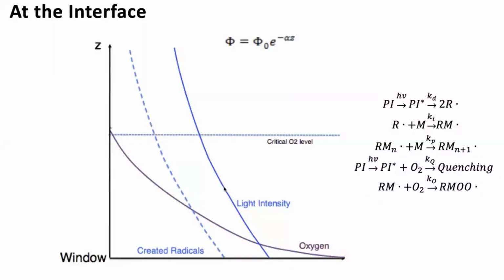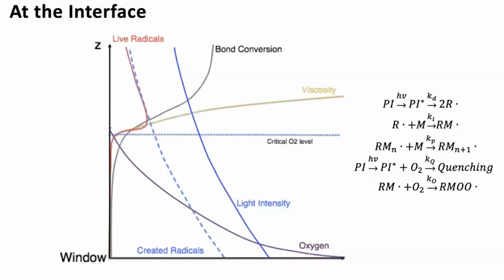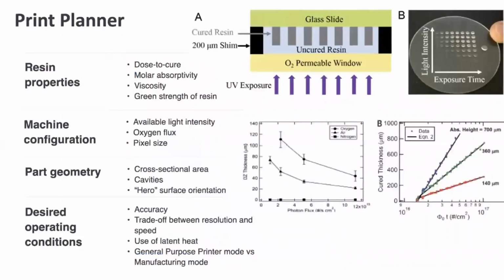That light is triggering a decomposition of an initiator that generates radicals, and so the radical concentration basically tracks with the light concentration. Those radicals can do one of two things. It can initiate a polymerization, but if there's any oxygen present, the rate constant for quenching of that radical is way greater than the initiation of a polymerization. And so what happens is, until the oxygen concentration gets below a certain level, there's no reaction. And then once the oxygen concentration drops below that level, then you have the forward polymerization where you get bond conversion, viscosity goes through the roof. And that gap, this distance, is really the definition of the dead zone.